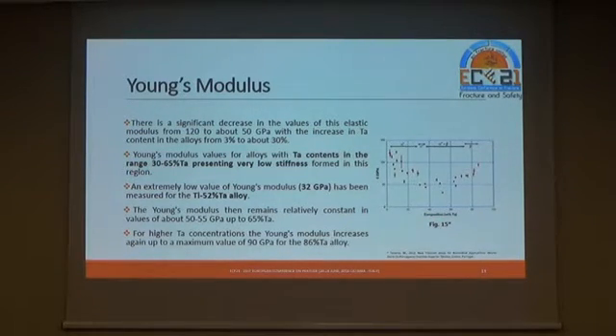And extremely low values of Young's modulus, 32 gigapascal, have been measured for the titanium 52% tantalum alloy. The Young's modulus remains relatively constant, at values between 50 and 55 gigapascal, up to 65% of tantalum. For higher tantalum concentrations, the Young's modulus increases again up to the maximum value of 90 gigapascal for the 86% tantalum one.